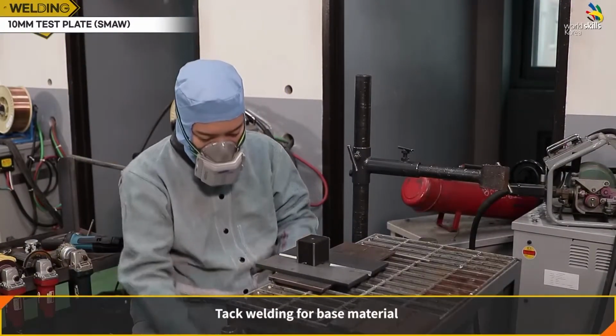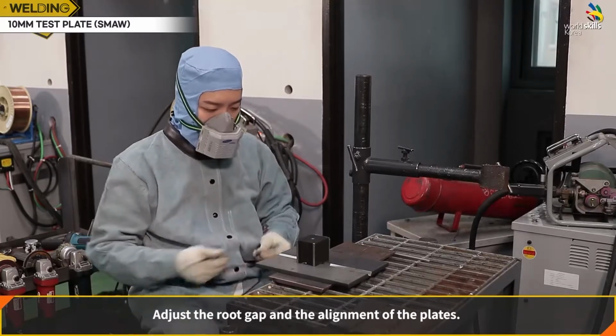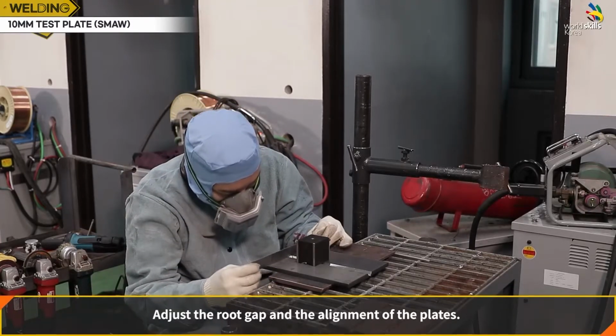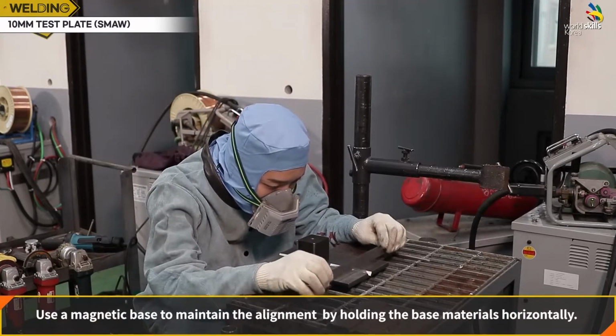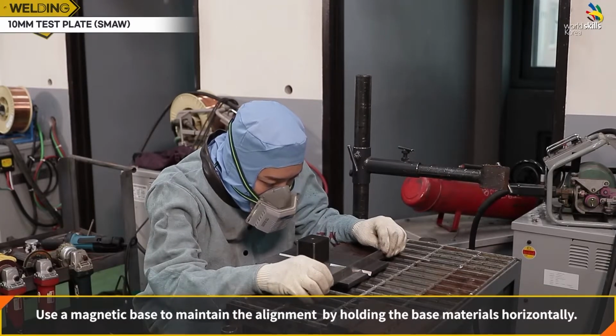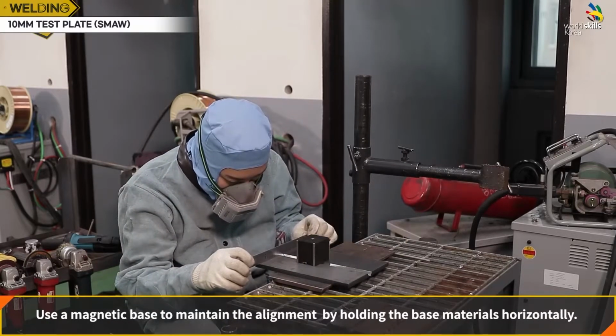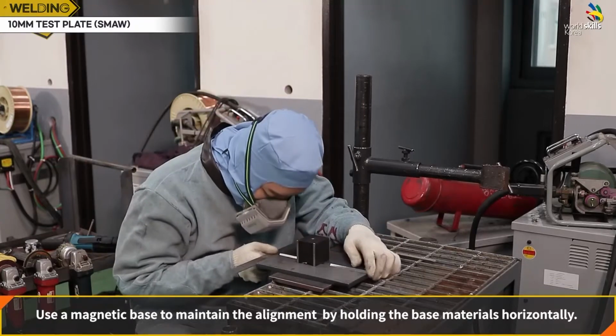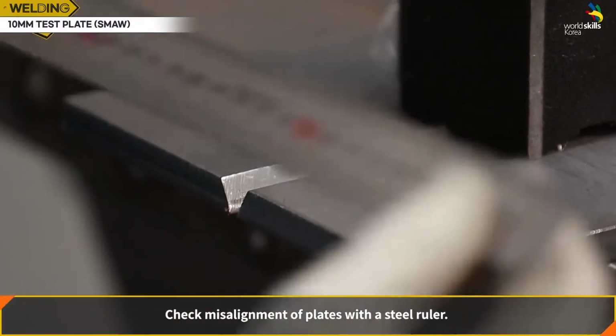Tack welding for base material. Adjust the root gap and the alignment of the plates. Use a magnetic base to maintain the alignment by holding the base materials horizontally. Check misalignment of plates with a steel ruler.